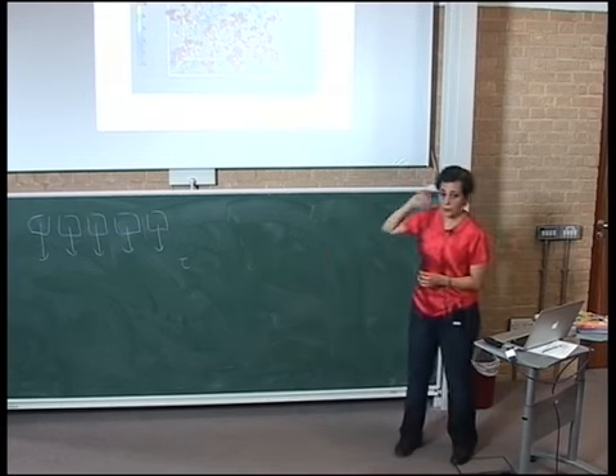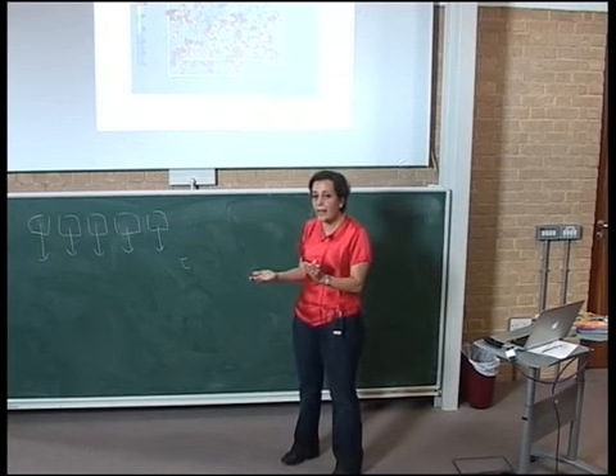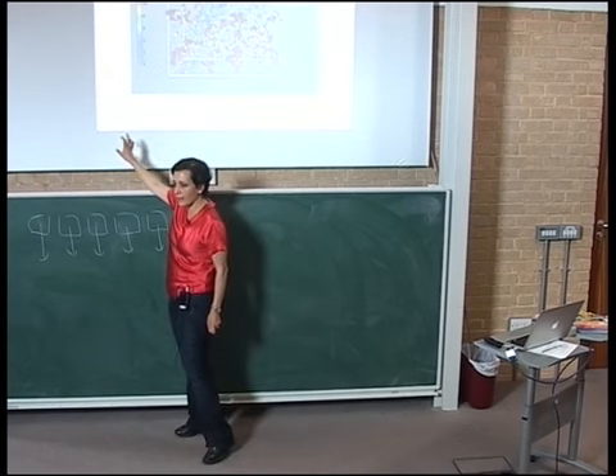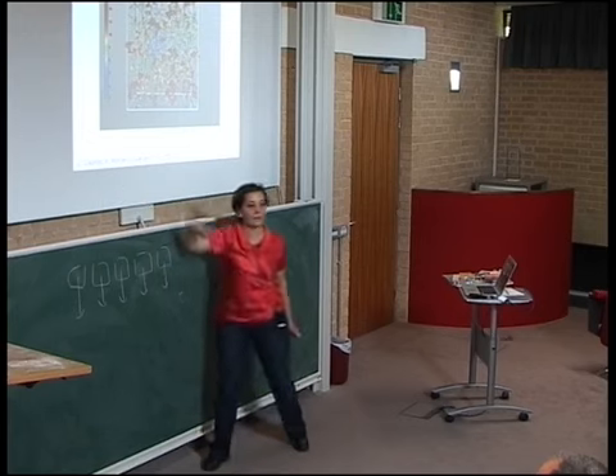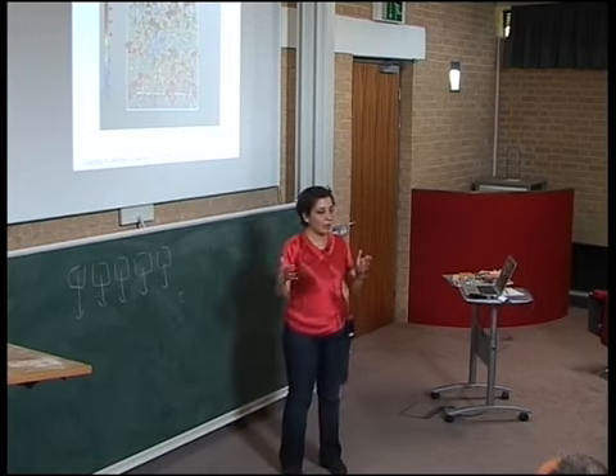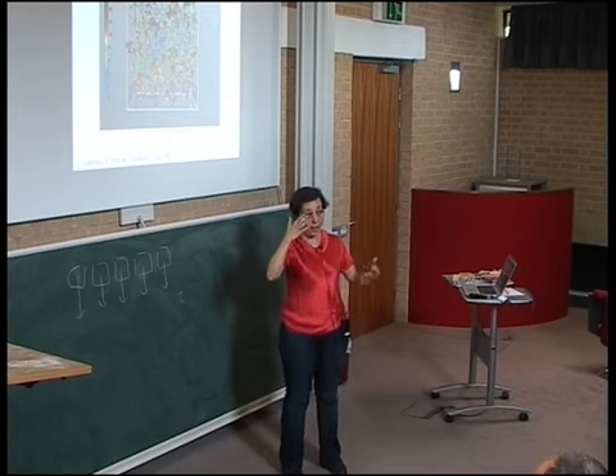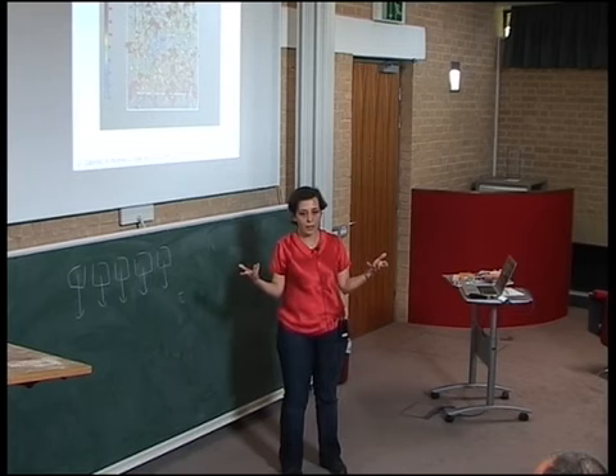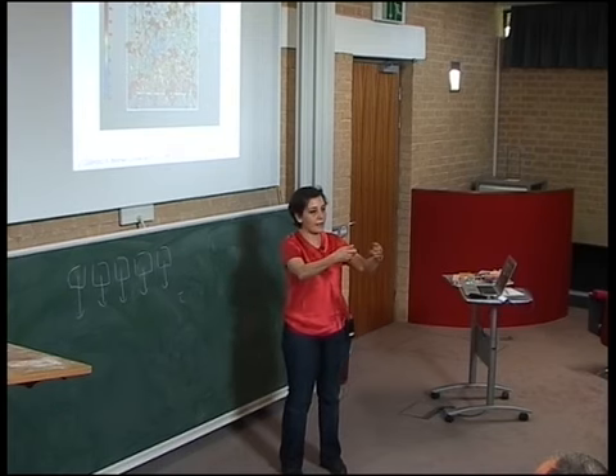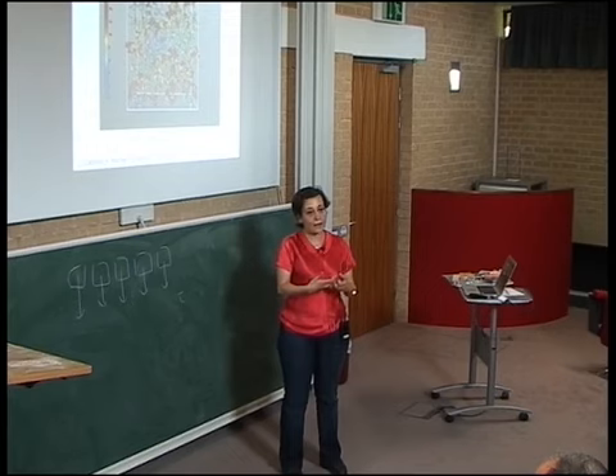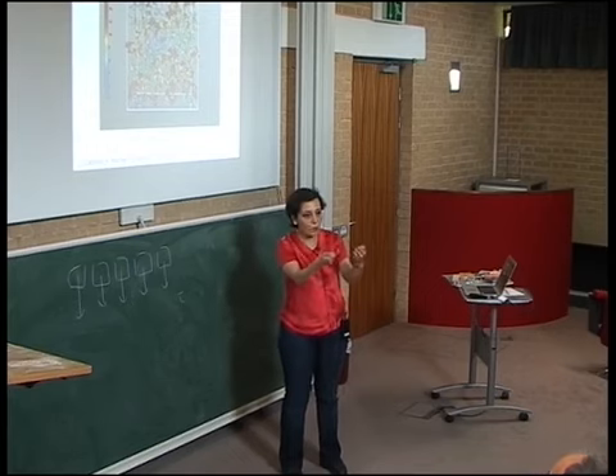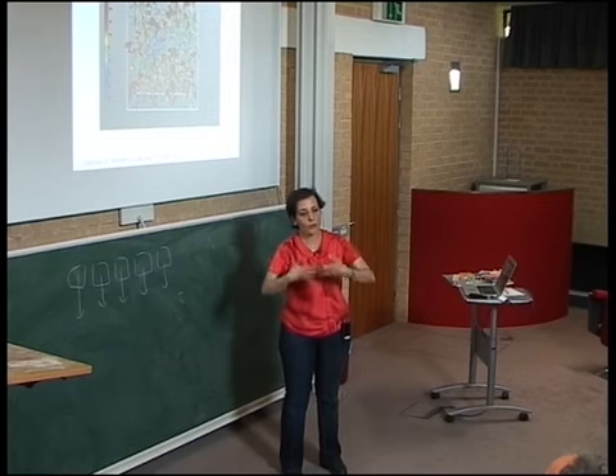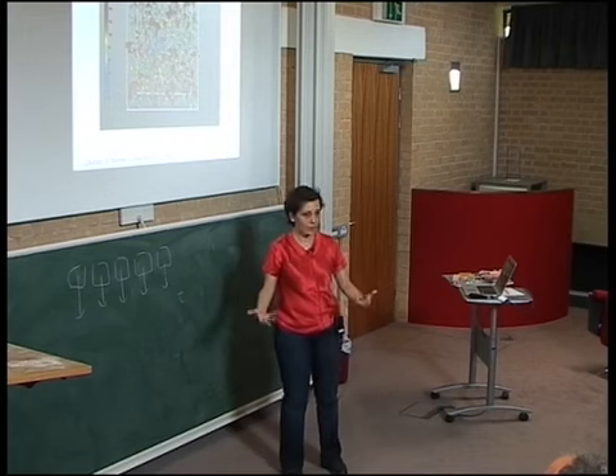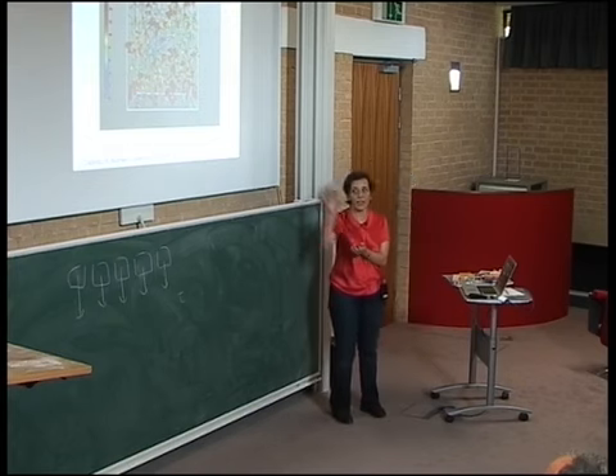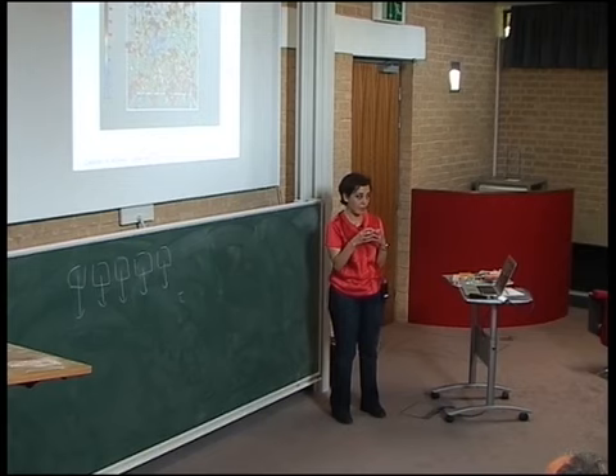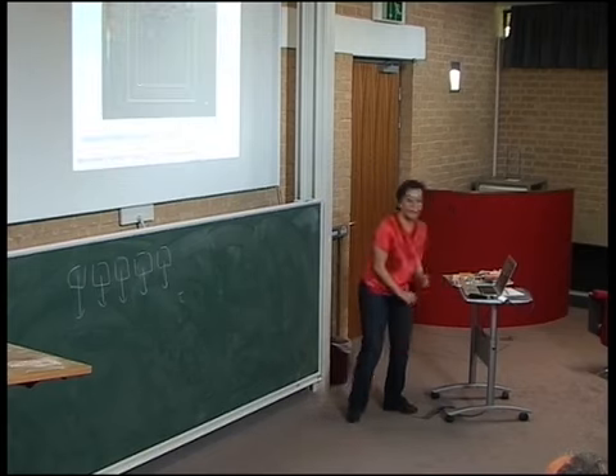So this is what you get. The other thing that you can say is, once I have these breaking events that happened in these thick parts, where can I see the consequences? Once I have filtered all this vibration, the restructuring of the network happens via this bond breaking. The effect of the restructuring is that I break something and then particles can move, right? So I can identify where the major restructuring processes, in terms of particle displacement, are taking place once I break one thing. If I use the thickness of the fibers to represent this feature, I get this other picture of my network.